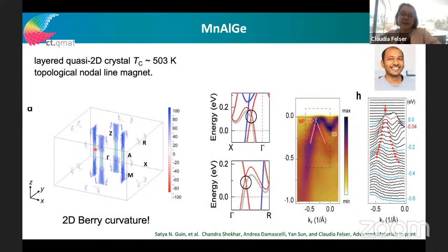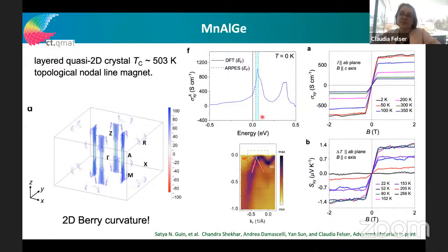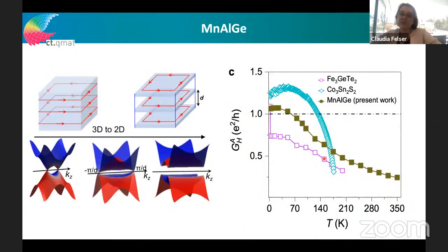So we find a very nice two-dimensional Berry curvature, surprisingly, which we haven't seen so nicely before. It's a nodal line metal. Luckily, the Fermi energy is slightly above the nodal line. Here we also have a high TC, which we like more than the low TCs, and we see in ARPES really the nodal line in this compound below the Fermi energy, and this is in nice agreement again with a large Hall effect, with a large Seebeck effect, in nice agreement with the DFT calculation and so on. Anyway, so this might be the material where we find a quantum anomalous Hall effect even at higher temperature.